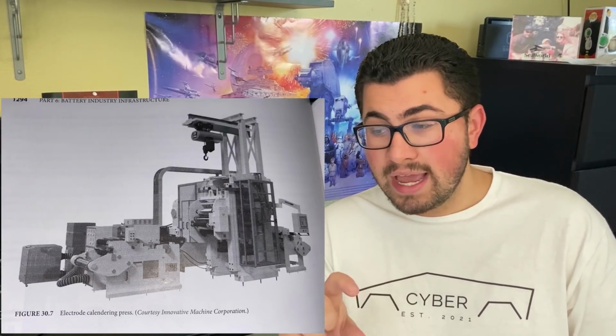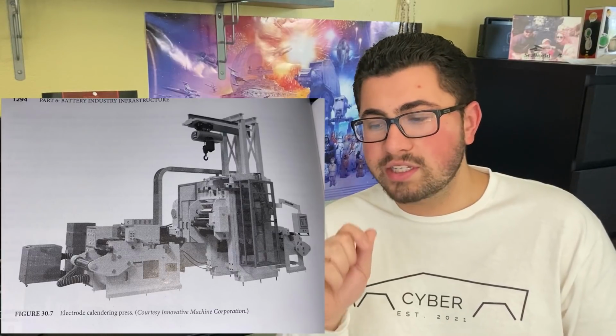As you're pulling it through, there's a process called fibrillization that occurs. What is fibrillization? It's basically the process where you take fibrils, or really fine fibers, and turn them into a matrix, basically a mesh. And that's how you create the electrode film. So what does that mean? Basically, you extrude it, you put pressure and stress on it, and that causes the state to change in the material. After that, you calender it, which means you take it through rollers and reduce the thickness to what size you want it to be.